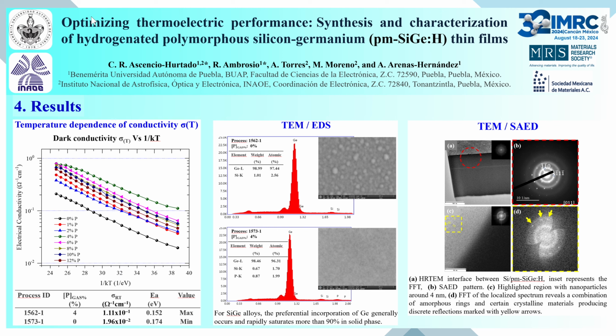At this point, it is pertinent to say that the deposition conditions of high pressure and high dilution rate promote the growth of nanocrystalline material, i.e., polymorphous material. Furthermore, we can see two distinct slopes in the plots of conductivity versus temperature, identifying the two-phase structure of the material. The amorphous and crystalline phases make a dominant contribution to the electrical conductivity of the material at lower and higher temperature respectively.